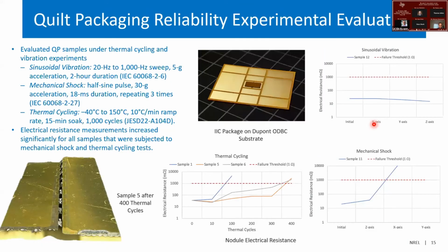And what we have done is we have looked at this kind of a package. So two chips quilted together on top of this DuPont organic direct bond copper substrate. We have subjected it to experimental reliability evaluations, sinusoidal vibration, mechanical shock, thermal cycling, following all the standards that are listed here. And we have performed electrical resistance measurements after the cycling. So sinusoidal vibration looks like it's looking fairly flat line here, but mechanical shock and thermal cycling can be fairly stringent, and based on resistance measurements of 1 ohm and higher, it's a definition of a failure threshold.